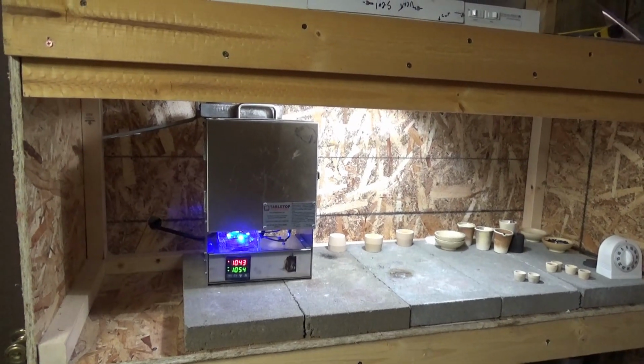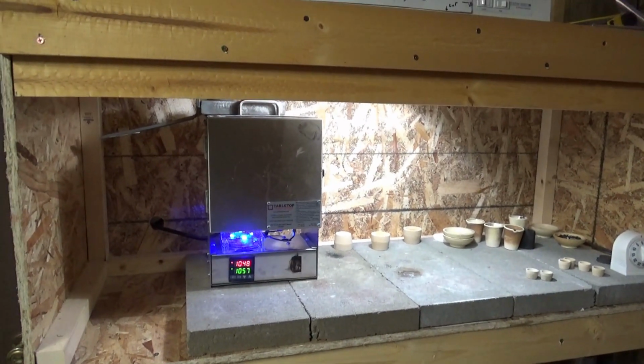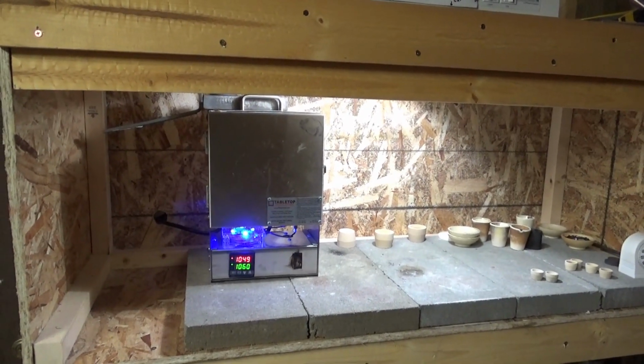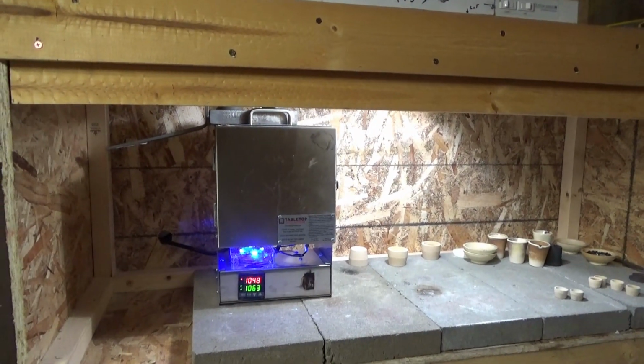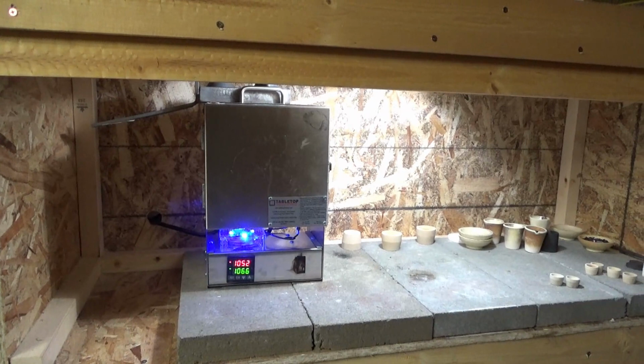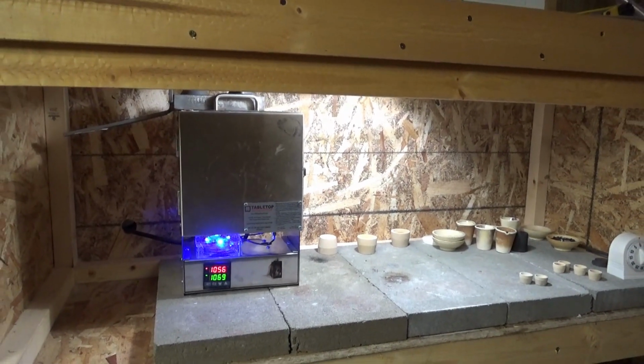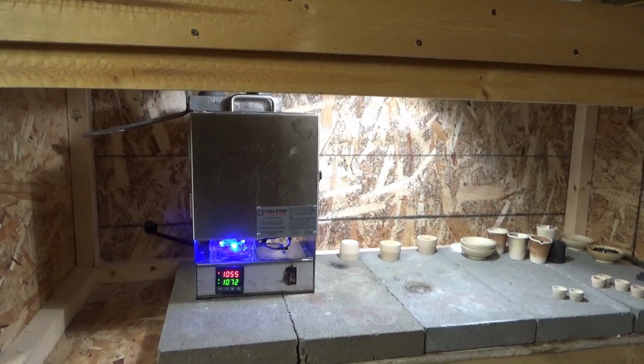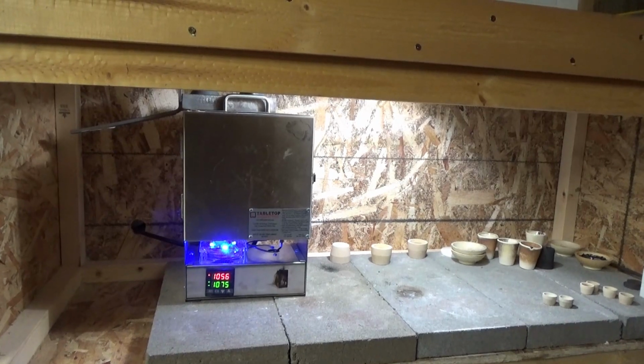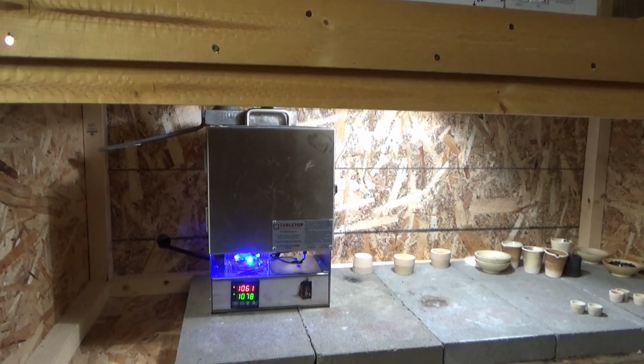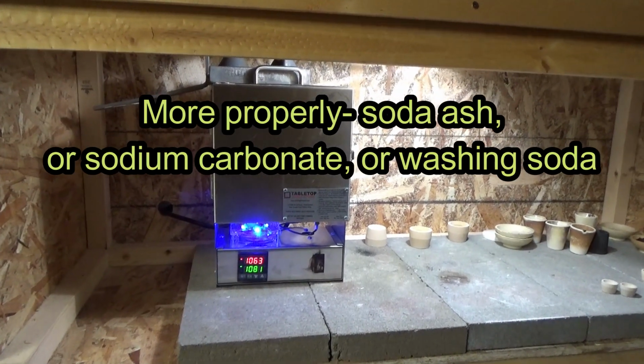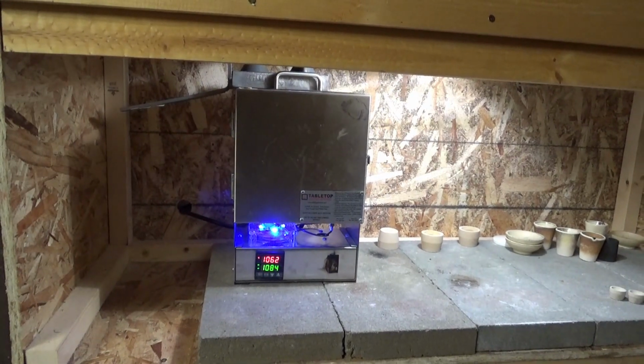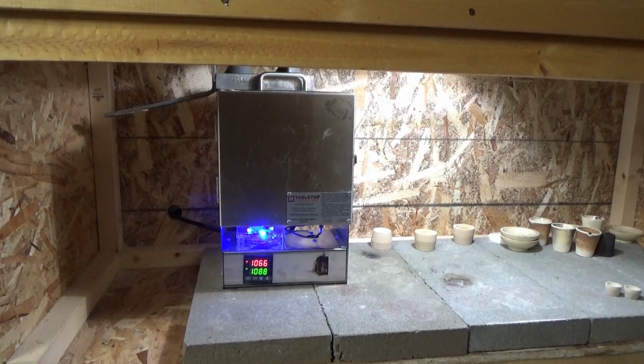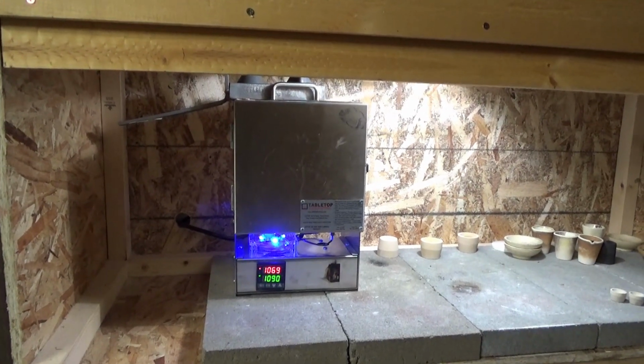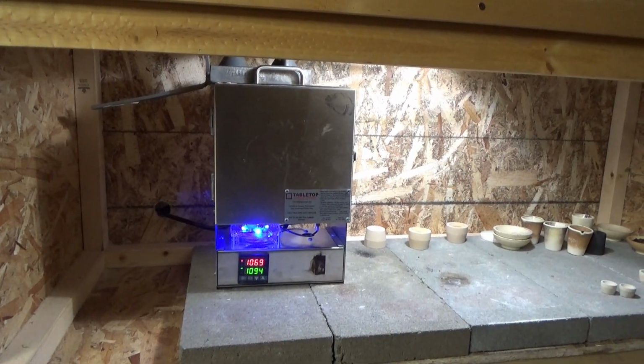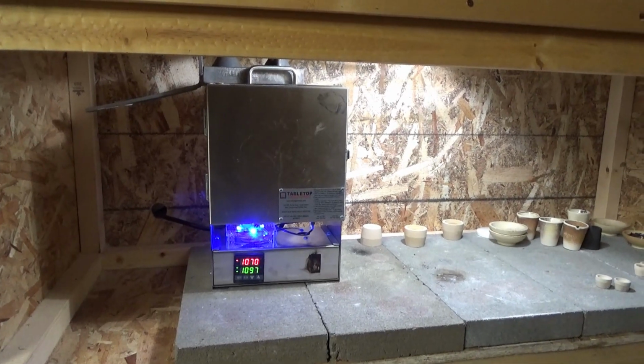Well, I'm waiting here longer, so I did some calculations to kill some time to try and determine, assuming that this works, how expensive is this going to be? So first of all, we have to figure roughly how much consumable materials we have. We're destroying the resin, okay? That runs about $13 a pound, and 1 pound will basically recover about an ounce of gold. Then we've got the soda and the silica. Those are pretty darn cheap, and we don't use too much of those. So those are $1.50 per ounce of gold recovered. The litharge, you use a lot more and it's more expensive. So that's going to run about $24 per ounce recovered.